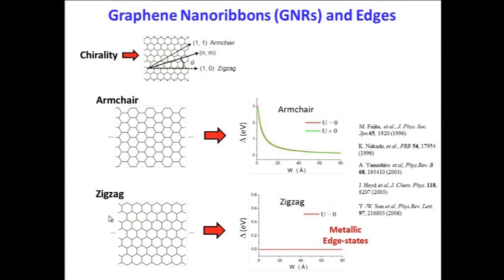But then people thought about it some more, and they realized that if you include electron-electron interactions, then what happens, because this edge state has a big density of states at the Fermi energy, it has been predicted that you would get a magnetic transition, that the edge would become ferromagnetic, and it was predicted that each edge would become ferromagnetic and that there would be an anti-ferromagnetic correlation between the two edges. And this anti-ferromagnetic correlation is predicted to open up an energy gap. And that energy gap was predicted to vary as 1/width. So here with the zigzag nanoribbon, you also are expected to get a 1/width energy gap dependence, but for very different reasons, very different physics.